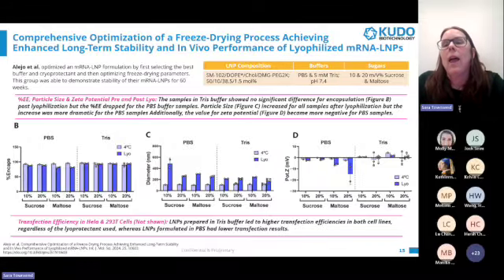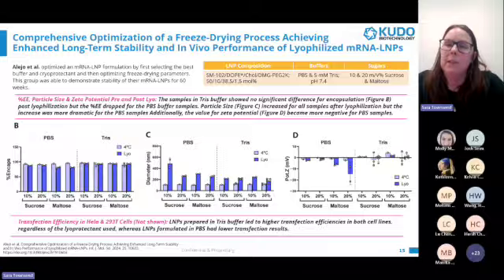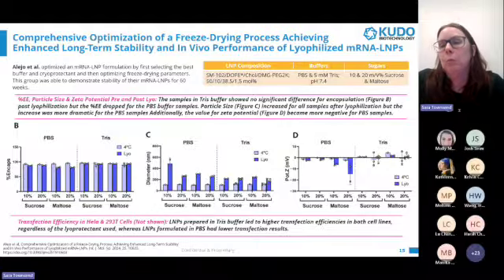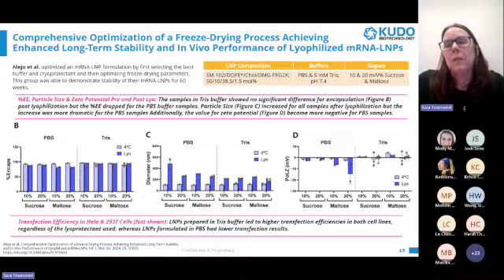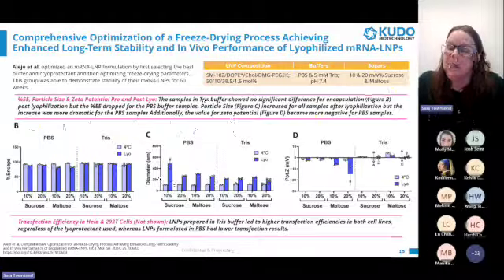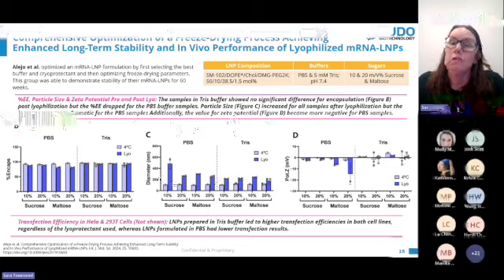So, a 2024 paper by Alejo et al. also investigated the use of Tris and PBS buffers for their formulation. Their cationic lipid was SM102. Similar to Mulewater et al., they observed that the transfection and percent encapsulation were lower for the PBS buffers and the zeta potential more negative than Tris.